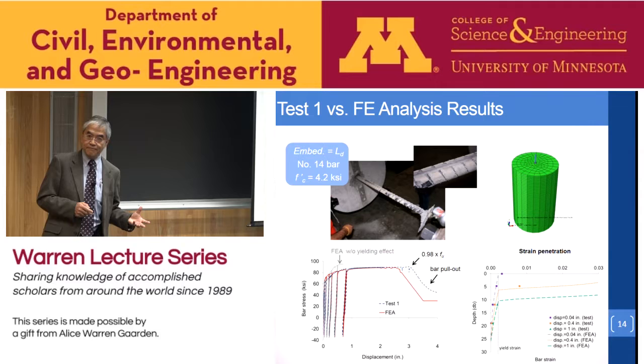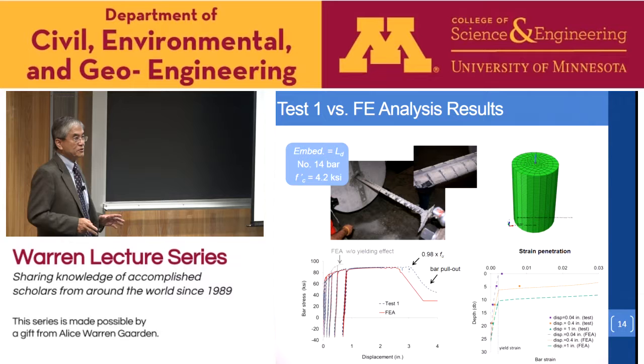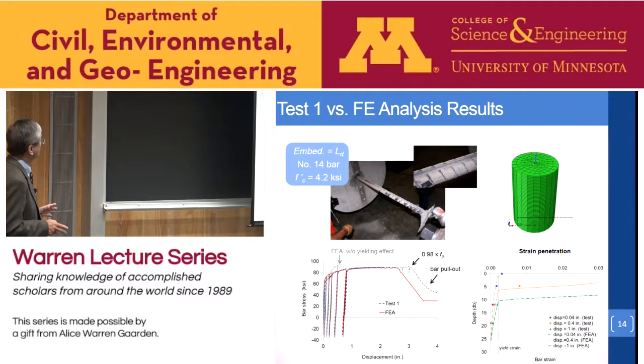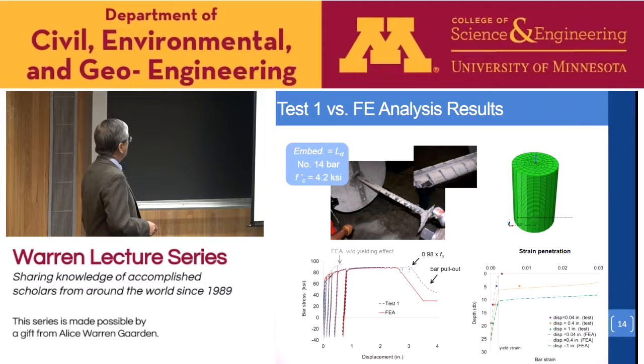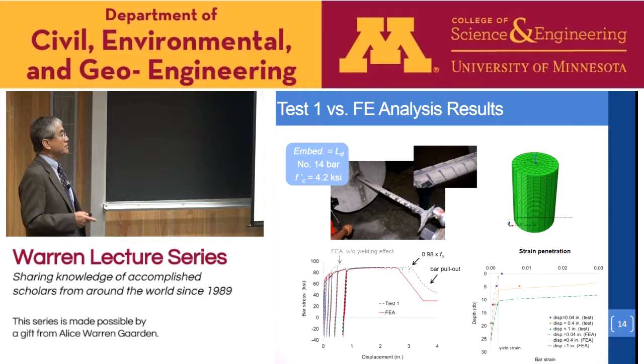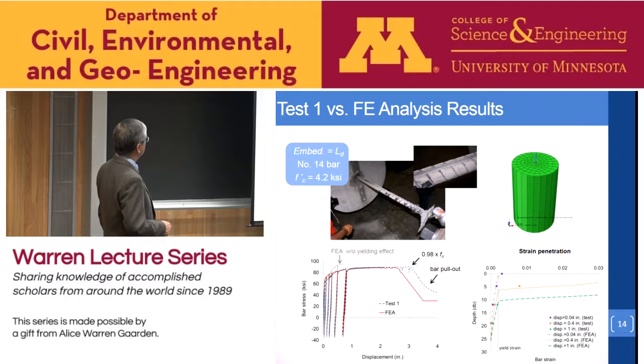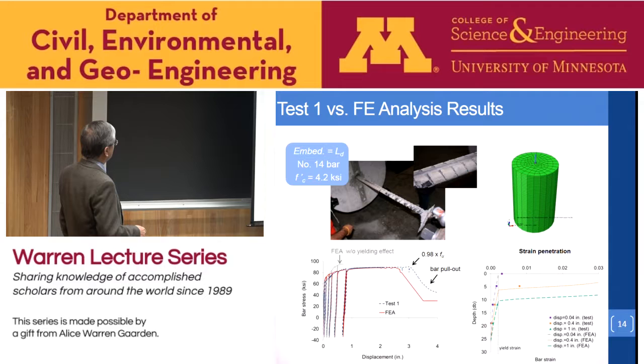We also did a large number of numerical studies with Monte Carlo simulation to show that the reliability index for the AASHTO is really lower than what we would like to have. Okay. So we validate this with our finite element model. You can see that this finite element model can predict that. And accounting for the yielding of the bar is also very important here. If we do not account for the yielding of the bar, okay, we will reach this point rather than the pull-out failure, so it will fail by bar rupture instead. So you can see that yielding is a very important factor.